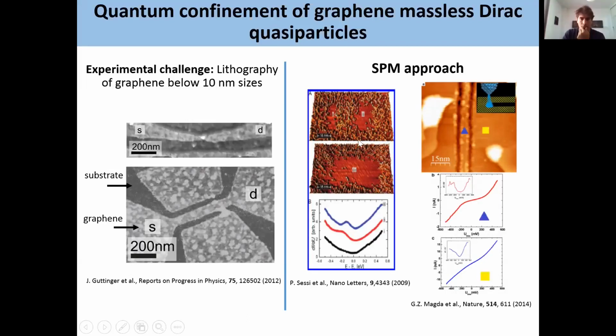So one of the first experiments was to hydrogenate the whole surface. You make this graphene, that's the idea behind it, cover everything with hydrogen, and then remove hydrogen with the STM tip. You apply some pulse, and then you remove, as you see here. And what they were observing was some changes in the electronic spectra of graphene. So that was the attempt.